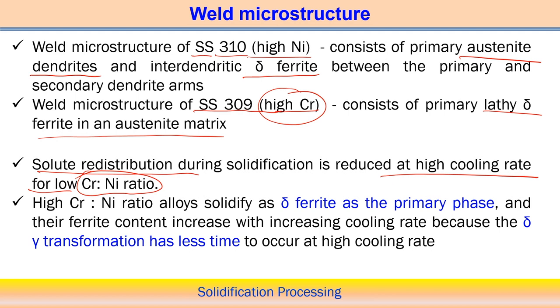But when the chromium nickel ratio is much higher, the alloy solidifies with delta ferrite as the primary phase. So it depends on the solute content, or the ratio of chromium and nickel, that we get, at the high cooling rate. Therefore, in these cases the redistribution behavior of the solute is different, and we are getting different phases also. So a high chromium nickel ratio alloy solidifies with delta ferrite as the primary phase, and the delta ferrite content increases with increasing cooling rate.